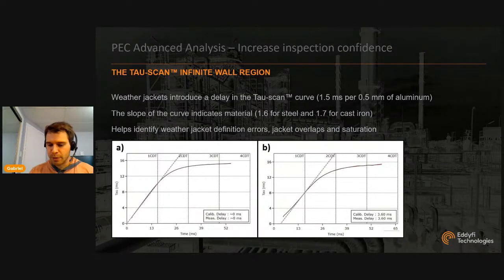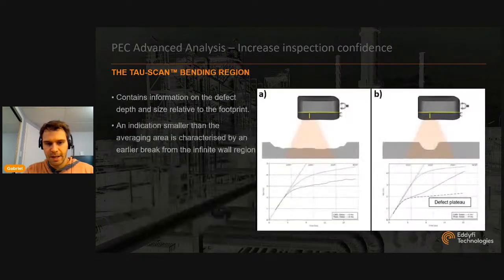This part also helps identify weather jacket errors. So if you're scanning over a component that's thought to have an aluminum weather jacket, but you have no measurement delay or no calibration delay, then you know that the definition of the component is perhaps wrong. Same thing for jacket overlaps. So if you've got half a millimeter of aluminum, 1.5 milliseconds of signal delay, then if you scan over an area with a jacket overlap, you're probably going to have around 3 milliseconds of jacket delay.